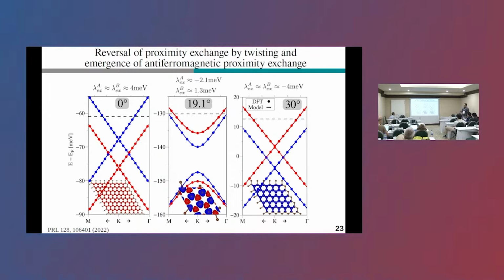And what is even more remarkable is that at a certain twist angle, this 19.1 degree, you can actually realize antiferromagnetic proximity exchange in graphene, as we can see here, this very nice sublattice character of, say, positive and negative spin polarization on the graphene.